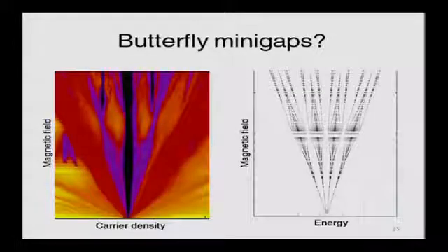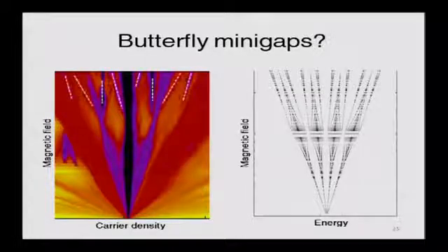So if we make the comparison with our theoretical calculation, what we can quickly see is that we're seeing these various features which trace just like these new gaps that are opening up in the fine structure of these levels due to this interplay between a periodic potential and a magnetic field. So in a sense, this is the first glimpse of this Hofstadter butterfly in a condensed matter system, where we've just used this superlattice to engineer the lattice to be the right size.